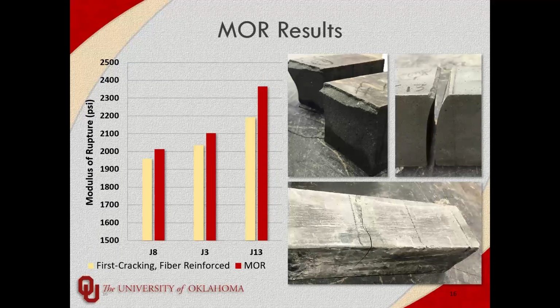Our modulus of rupture results were a little interesting. With our compressive strengths, all the mixes seem to be relatively similar. J3 outperformed them, but not by a whole lot. But for the modulus of rupture, J13 really outperformed everything in bending, which was surprising. And J3 and J8 were relatively similar.